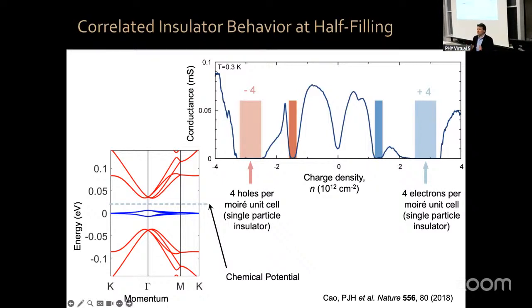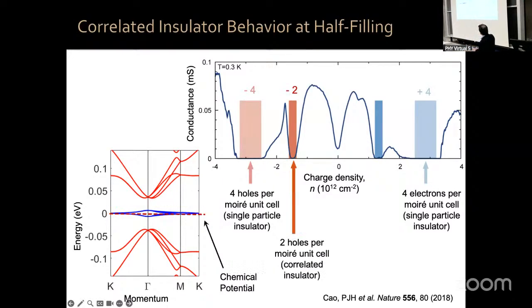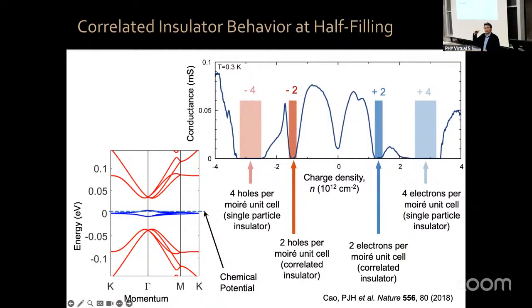Now the surprise came when we did the following. If you place 2 holes per moiré unit cell, or 2 electrons per moiré unit cell, now my chemical potential is in a region somewhere in this flat band with a very high density of states. This should be a very good metal and should conduct electricity very well. However, the conductance is zero.